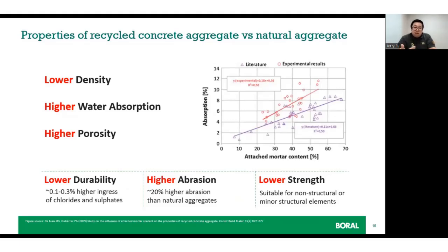The residual adhered mortar on aggregate is a main factor affecting properties such as density, porosity, and water absorption of recycled aggregates. The density of recycled aggregates is generally lower than natural aggregates. This is due to the adhered mortar, which is less dense than the underlying natural aggregate. The variation in density can depend on the specific aggregate in question.